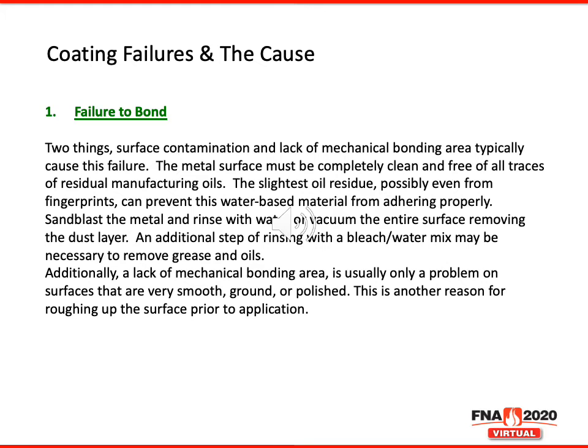At this point, it is important to note coating failures and their cause. The number one coating failure is failure to bond. Two conditions typically cause this type of failure: surface contamination, or poor surface preparation, and lack of mechanical bonding area. As previously mentioned, surface preparation is the most important step in any coating application. The slightest oil residue or dust will prevent these water-based materials from adhering properly. Additionally, a lack of mechanical bonding area is usually only a problem on surfaces that are very smooth, ground, or polished. This is another reason for roughing up the surface prior to application, or surface preparation.